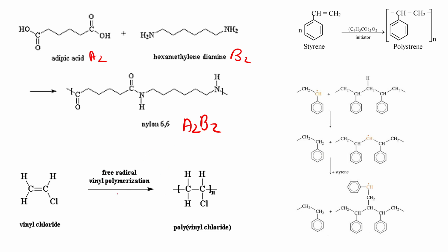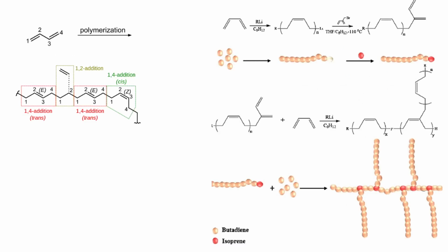And for free radical polymerization, PVC is very well known. So PVC goes by free radical polymerization. And for polystyrene also, mainly radical based polymerization is used, with the help of an initiator. So with a peroxide bond, the peroxide is used as initiator, it generates O dot followed by C dot, and when C dot is generated, that can now undergo this polymerization. That's how polystyrenes are made.